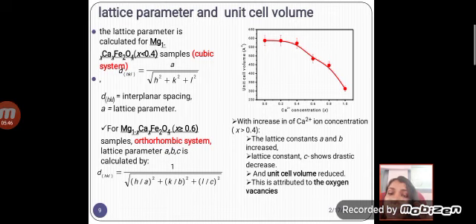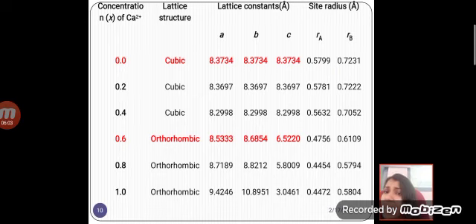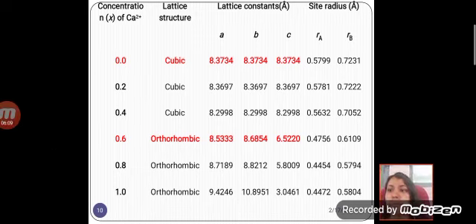So we can see that with increase in calcium concentration, the lattice constants a and b increased, while the lattice constant c shows a drastic decrease. And the unit cell volume also shows a gradual decrease, which is attributed to the oxygen vacancies within the sample. And we can see the tabulation form; the present table shows the concentration of the calcium, the lattice structure and the lattice constants.